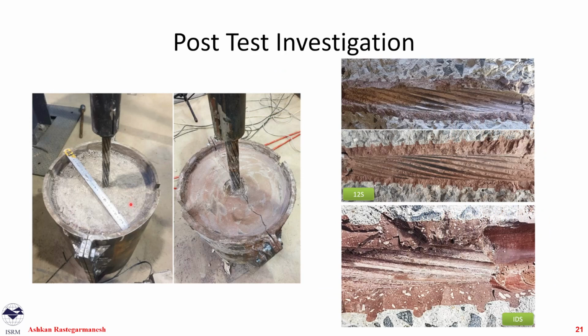After the test, we broke our samples. One of the main observations was that we get lots of radial cracking that starts from one of these flanges, reaches the cable, and continues to the other flange, regardless of what torque we put on these nuts. And this only happened in the bigger cable. So in super strand cables, which are smaller, this didn't happen.